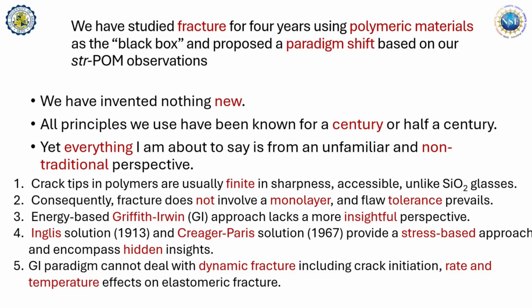There are 5 essential conclusions I'm making, none of which was something very familiar to us previously. First, our dear polymer offered us the chance that your crack tip is blunt, is finite, not sharp. This means your fracture does not involve just one monolayer. Thirdly, we recognize, this is discussing my perspective article, that the traditional popular approach, energy-based, lacks a more insightful perspective. Fourth, all the new perspective is buried in the paper that's over 100 years old. Fifth, the framework we are familiar with in fracture mechanics generally cannot deal with the fact, in my elastomer case, that my strength, my toughness is rate and temperature dependent.